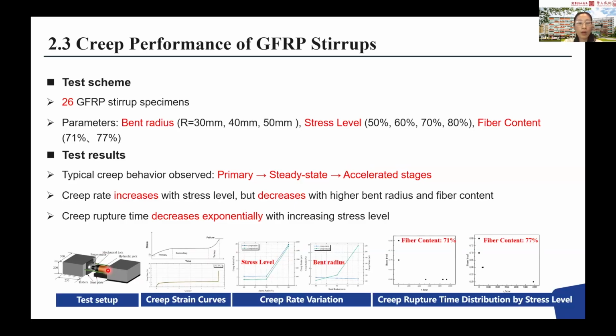bond effect. And the typical creep behavior, as shown in this figure, typically has 3 stages. The primary stage is when, during a short duration, we have an increment, and then we go into the steady distribution of strain, and then right close to the rupture, we find that the strain has an abrupt increment. And also, we found that when we vary the stress level, the duration of the creep will be